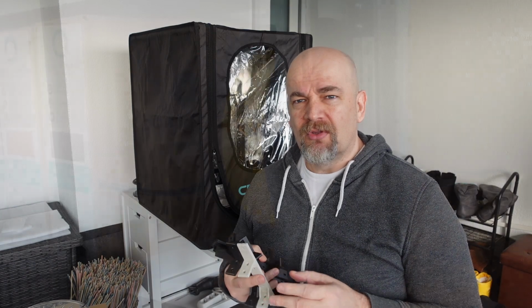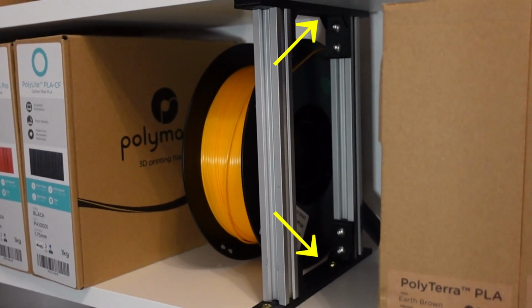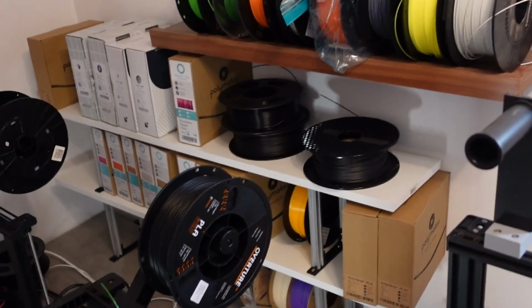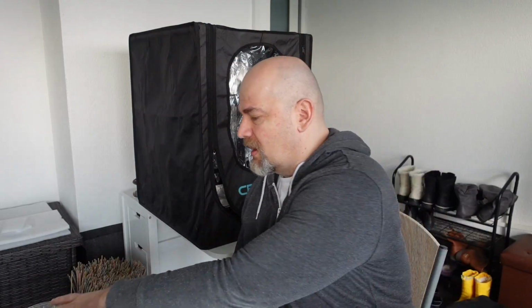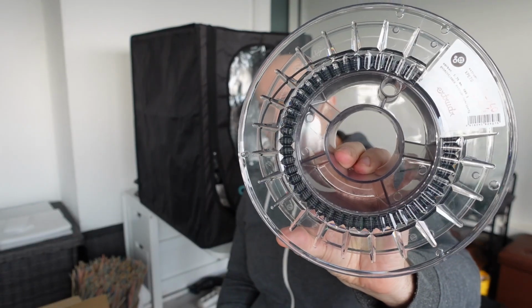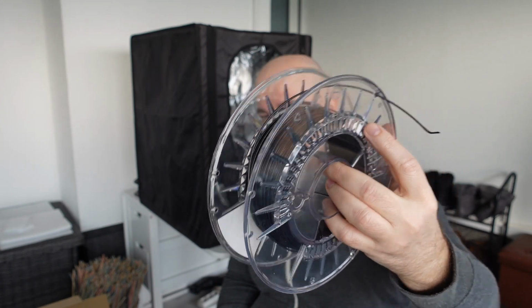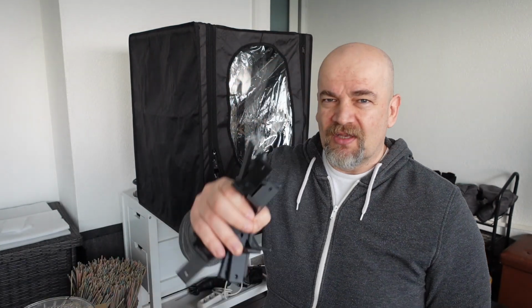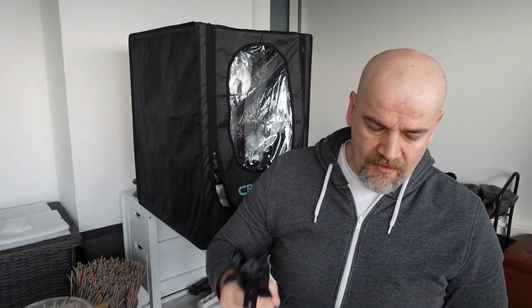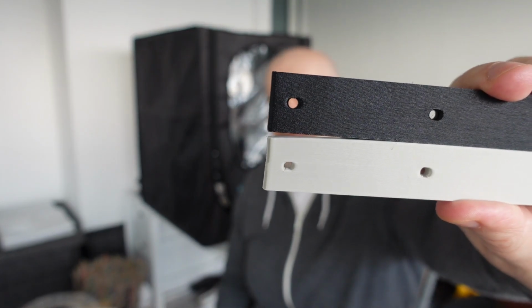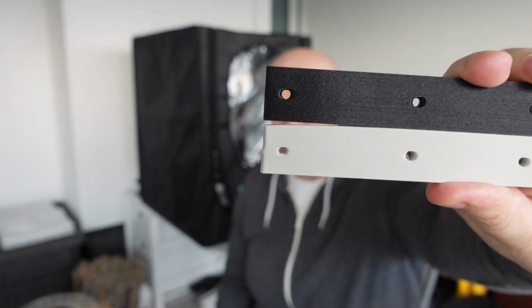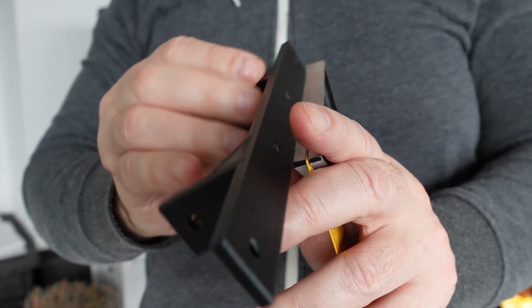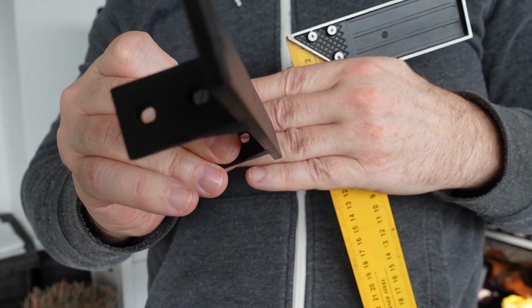And I already mentioned that I wanted to do more printings because I wanted to see if everything is okay with the 0.6 mm nozzle and this carbon filament. And I used almost the whole spool. That's why I was searching for the weight of the spool, to see how much filament I have on it. And I printed these shelf holders. This is a second set, because originally I wanted to print them from ASA, and since I'm using 0.3 mm layer height, I couldn't get nice prints with ASA. I always had this warping, you know, if you're not familiar, bigger layer height, more tendency to warping. And these are perfectly straight, great prints, but again, don't forget, use a bigger nozzle, not 0.4 mm.